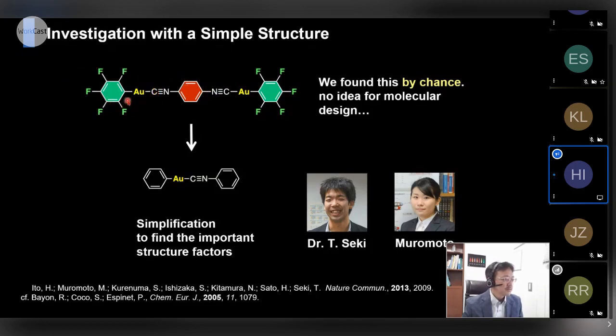This compound has two pentafluorophenyl groups, two gold metal centers, and one isocyanobenzene structure. Really, the structure looks very strange, but we don't know what the most important point is. So for the next step, we tried to make a more simplified compound to detect the most important point for the mechanochromic luminescence property of gold isocyanide complexes.